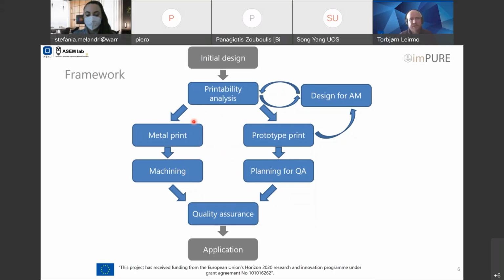For this metal print lane, we propose going for metal print, and of course you need some machining first because the roughness and the tolerances of this metal print is not good enough for the injection molding machine. So we need to do some machining and eroding for the surface to be good enough for the injection mold. And this all leads to quality assurance before you can go to application. Now, as you can see, these two lanes are really the most important part of this framework, which means that this prototyping is also part of the entire processing chain.